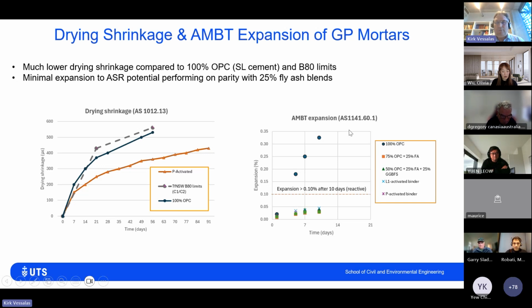I mentioned earlier about the opportunity of using this technology to mitigate ASR. So this is the accelerated mortar bar test. It's an expansion test. It's a rapid screening test. These dark dots here, the blue dots, represent just a standard 100% ordinary Portland cement system. And when we start introducing fly ash into the blends, whether it's a binary or ternary blend, you start to see that the liquid activated and the powder activated systems are performing on par. So we will continue to monitor this expansion up to 21 days, and beyond that, we'll take it right out to 56 days to see what happens with obviously the mitigation around expansive aggregate. So in this particular test, just clarifying that we have used a reactive aggregate that's prone to expansion.